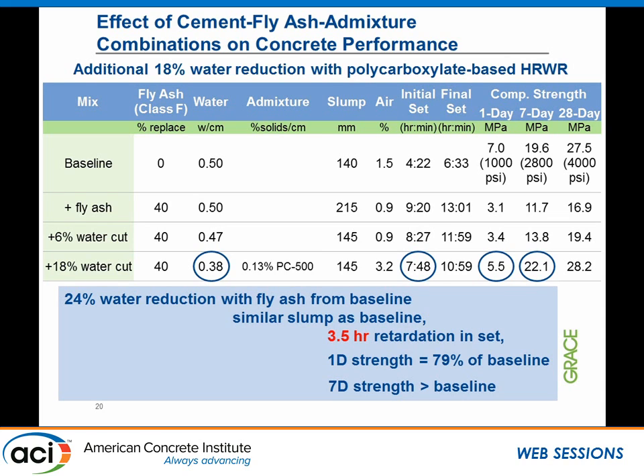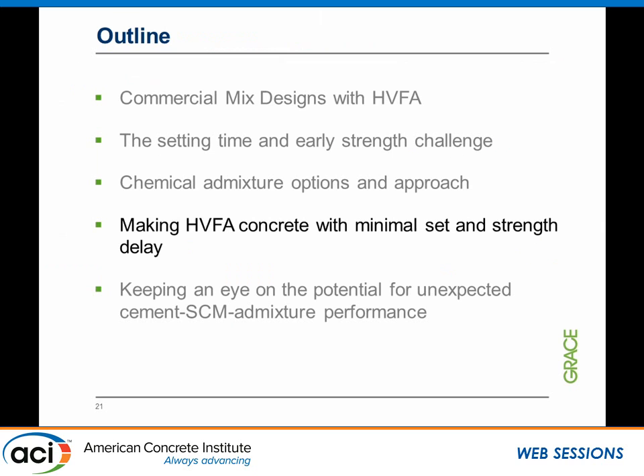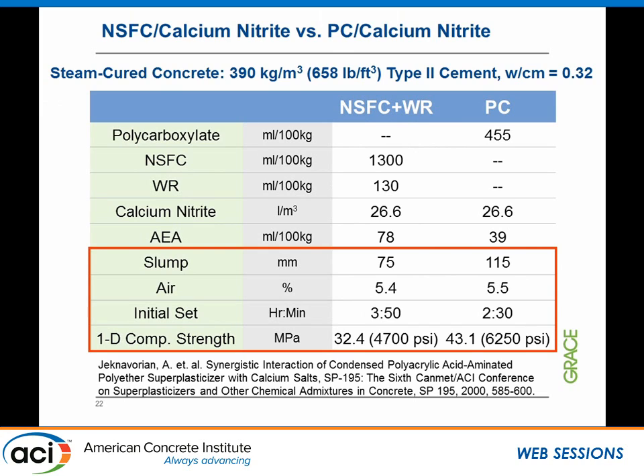In terms of strength, we are getting better. We're almost 80% of what we get from the baseline. And by 7 days, we're actually higher than the baseline. So we're getting closer and closer. So what else can we do to make this concrete meeting the targets that we need? And here we show you one example that we got in the field.